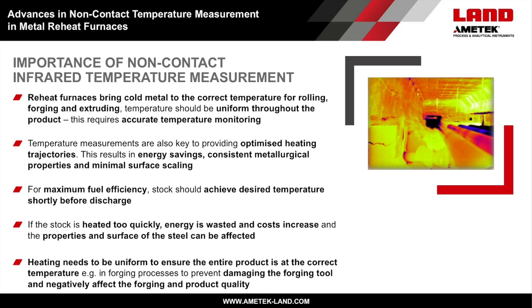For maximum fuel efficiency, stock should achieve desired temperatures shortly before discharge. If the stock is heated too quickly, energy is wasted and costs increase, and the properties and the surface of the stock can be affected. Heating needs to be uniform to ensure the entire product is at the correct temperature, for example in forging processes, to prevent damage to the forging tool and negative effects on the forging and product quality.